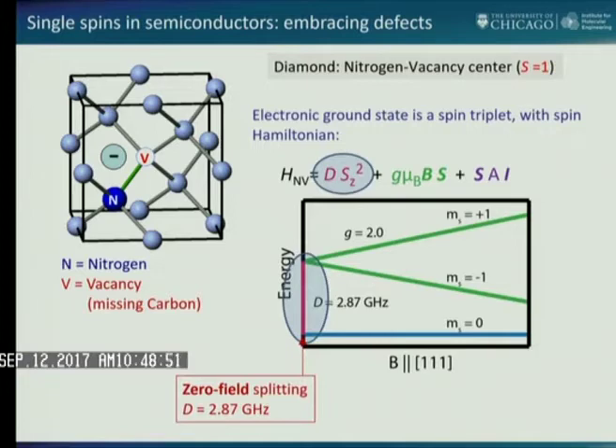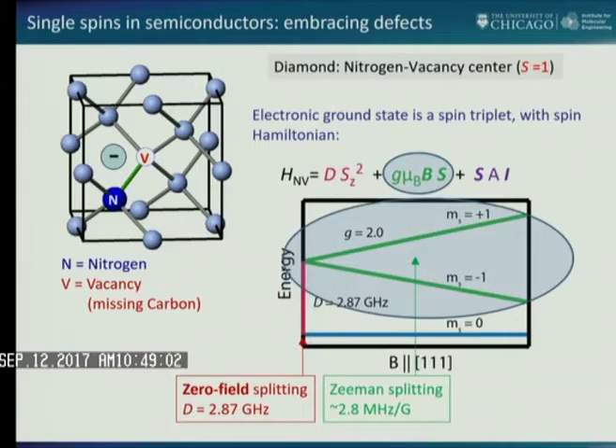And the reason I'm saying that is that's right in the telecom frequency. That's a microwave frequency. It's where all of your cell phones operate. It's a very easy frequency to control. You can tune it a little bit with an applied magnetic field if you want to. You can change these separating spin levels by a few megahertz per Gauss, so they're very tunable with refrigerator magnets, very low fields. You don't need much.